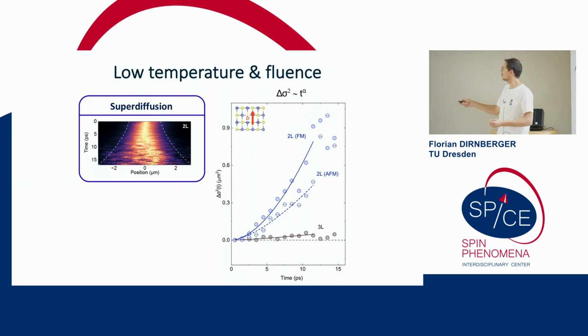So you can see here in the bilayer, the velocity is just significantly larger, and all of this super diffusive behavior is gone. And then the second striking phenomenon that we do see in chromium sulfide bromide at low temperatures happens when we move even further to a 10-layer crystal, again under the exact same experimental conditions.